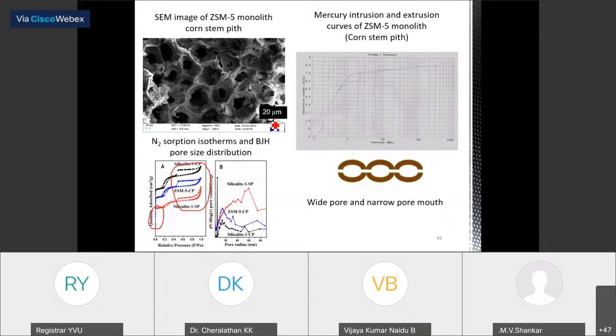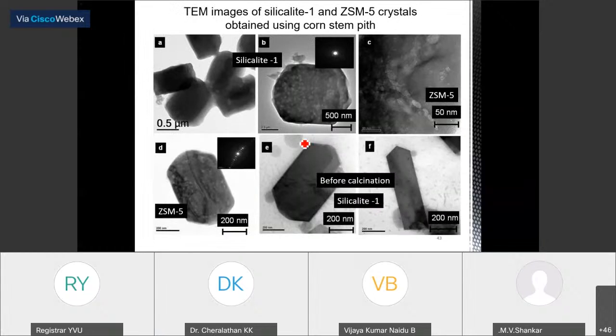Also, we have done mercury porosimetry to study the macropores present in this material, and we found that this material not only has micropores and mesopores, it also has macropores, which is looking like this. Wide pore and narrow pore mouth. So this mercury intrusion and extrusion curve shape indicates this kind of arrangement. And also we have done TEM analysis to find out whether it is having intracrystalline porosity or not. Yes, this is the zeolite crystal, and you can see these bright spots. They are all showing some pores are present on the zeolite crystal.